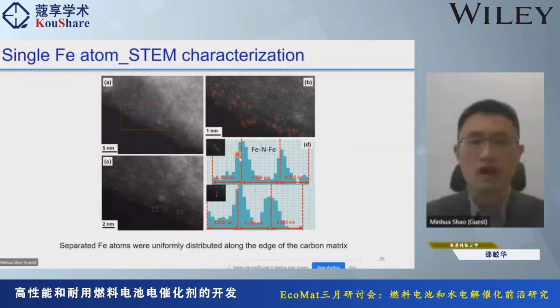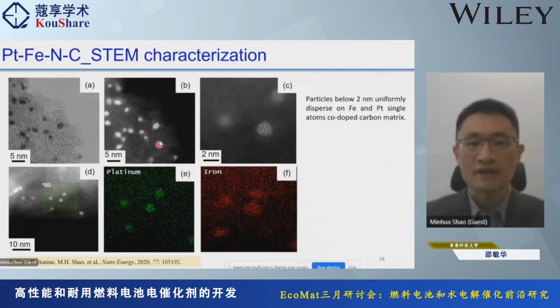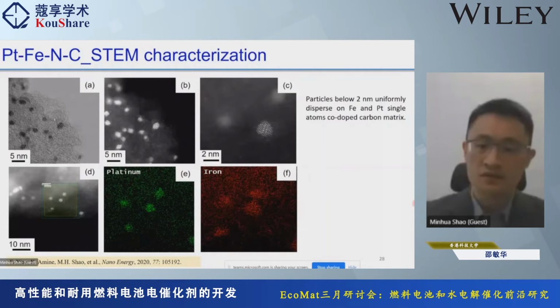And this is the further characterization of the single iron atom. Okay, so you can see that the iron distance can range from about 0.3 nanometer to 0.4 nanometer. So the 0.4 nanometer means that there is nitrogen coordination between two different iron atoms, and with 0.3 nanometer, that means the two irons do not have nitrogen coordination. Okay, so another go at details. So here are some of the TEM images showing the nanoparticles of platinum iron, and in addition the very small nanoparticles, about 2 nanometer. Okay, very, very small, and then you also have these single atoms. Okay, so there are a lot of single atoms, and the majority of single atoms are iron.